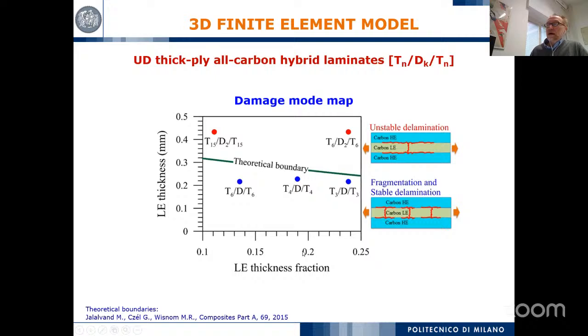ply can provide us the pseudo-ductile behavior, meaning when we can have fragmentation and stable delamination in the material that create this pseudo-ductility. So finally, the message is, this carbon-carbon hybrid laminate could be an interesting material because it's a single material in terms of fiber. We can create, and in some way we can control the pseudo-ductility, and further to this, we can also have